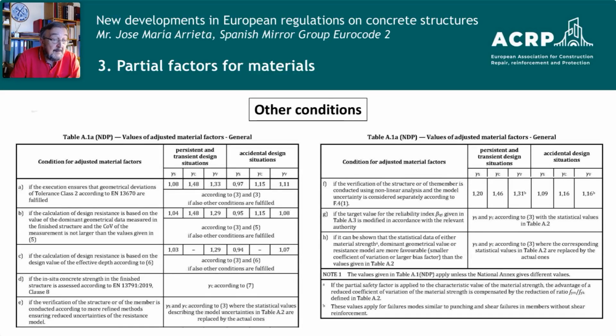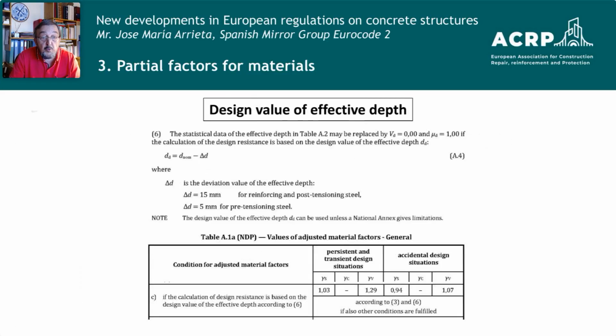In condition D, there is another typical situation of existing structures. If we use core tests, then we must reformulate the partial coefficient of the concrete, and you may find the instructions to do that. A particular case which improves the results is, for example, the use of a design value of the effective depth instead of a nominal value.